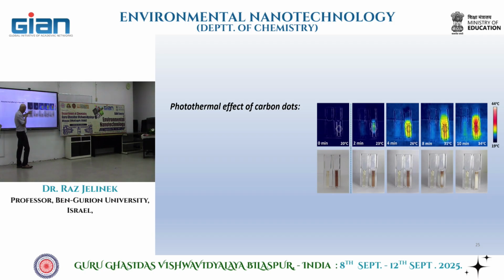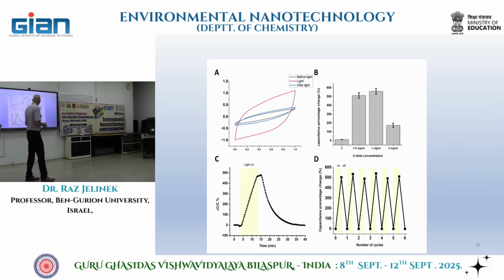Initially, nothing happens. At 2 minutes, the temperature goes up. And you see that the polymer becomes kind of cloudy because the polymer becomes hydrophobic. We shine more light, 4 minutes, the temperature starts going up here, 26 degrees, more cloudy. At 8 minutes, higher temperature, you see it's even more cloudy here. At 10 minutes we get 34 degrees, and this is total phase transition. We don't even see the carbon dots because the polymer becomes like a gel, very cloudy. This is how we perform the experiments.